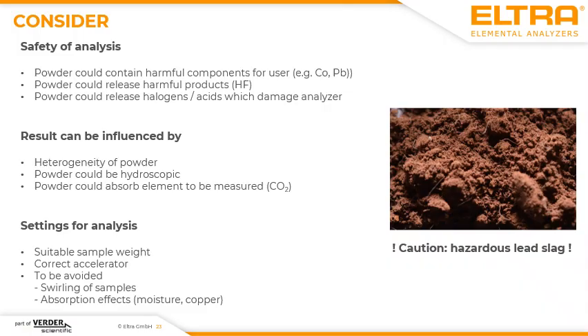Nevertheless, when you now think, okay, I can analyze my sample safely, and I also make sure that the heterogeneity is acceptable, and that no hygroscopic effect takes place, then you have to think of what is a suitable sample weight, what is a correct accelerator, and how can I avoid swirling of the sample because it is so finely divided, and which things do I have to consider when I would like to avoid absorption effects? For example, moisture and copper dust can falsify especially the sulfur results.